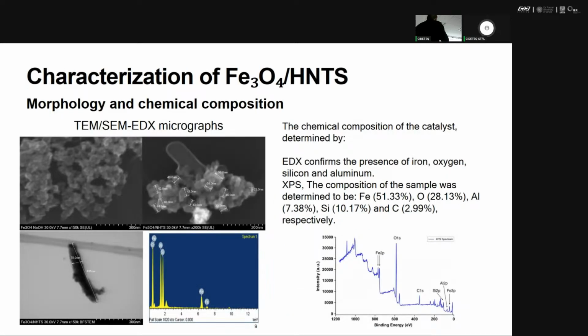For the characterization part, I synthesized this material. In this part, we can see the magnetite. As I said, it is a spherical particle. So it is very common that this material agglomerates. So it is a problem because it's a little more difficult to use for separation.